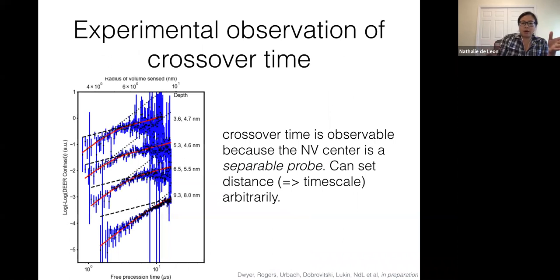Okay, so now armed with this theoretical model, we could go back into the data and look for NV centers where people had oversampled their coherence significantly. It turned out that we actually had this data for something like 4 NV centers. So here are 4 NV centers where we can see an experimental signature of this crossover time. These are NV centers at different depths. And what we see is that indeed at early times, we have something that fits to a slope of n equals 2, and at late times, it curves over to an n of around 2/3. So everything that I told you about actually isn't really special to NV centers at all.